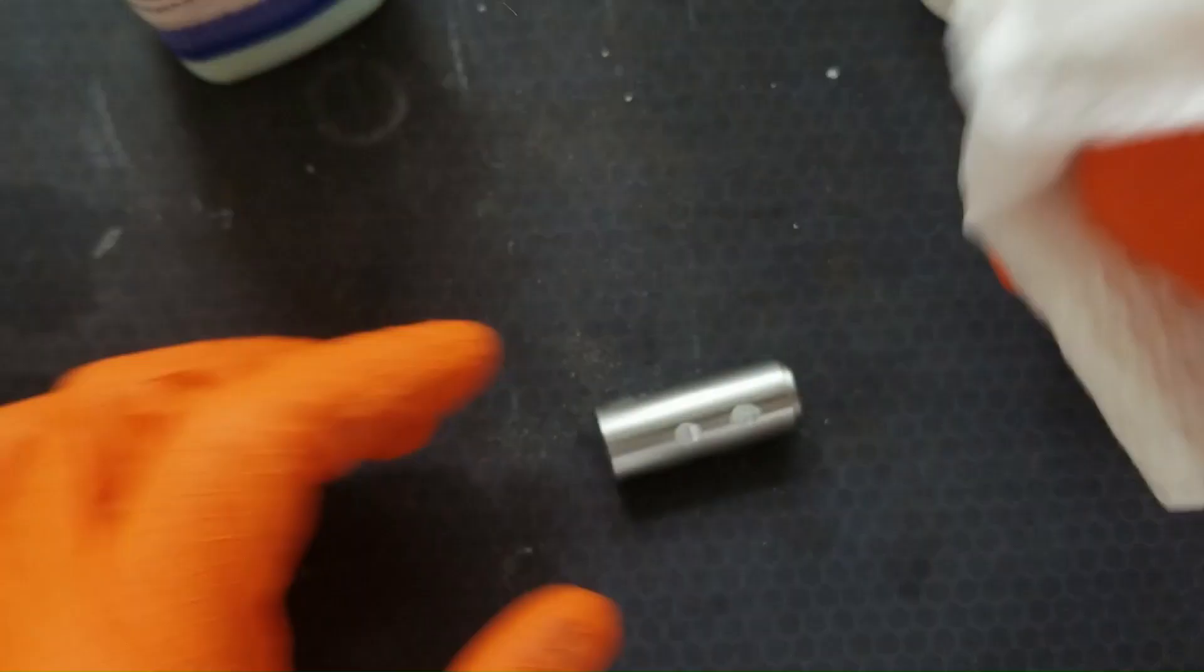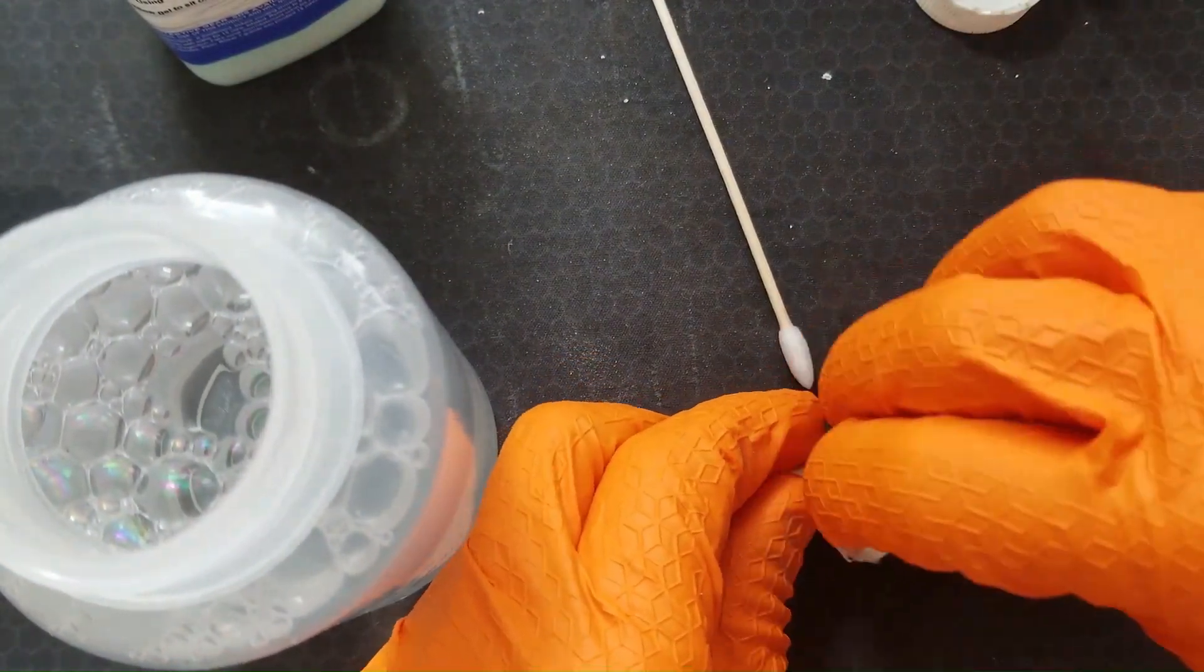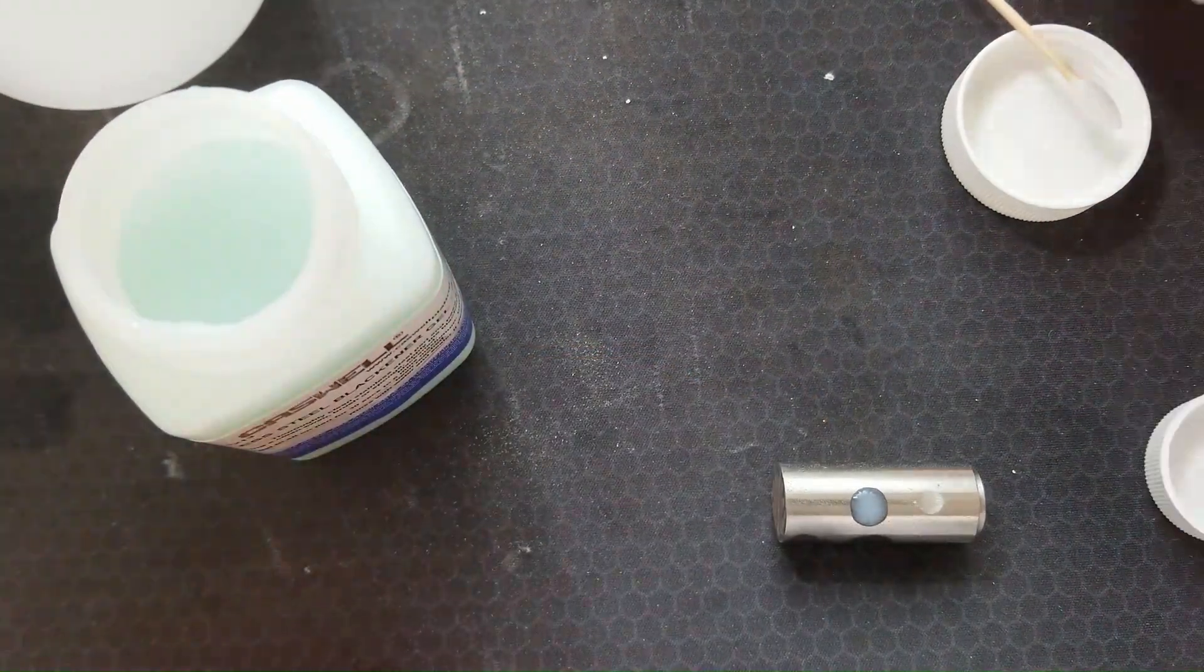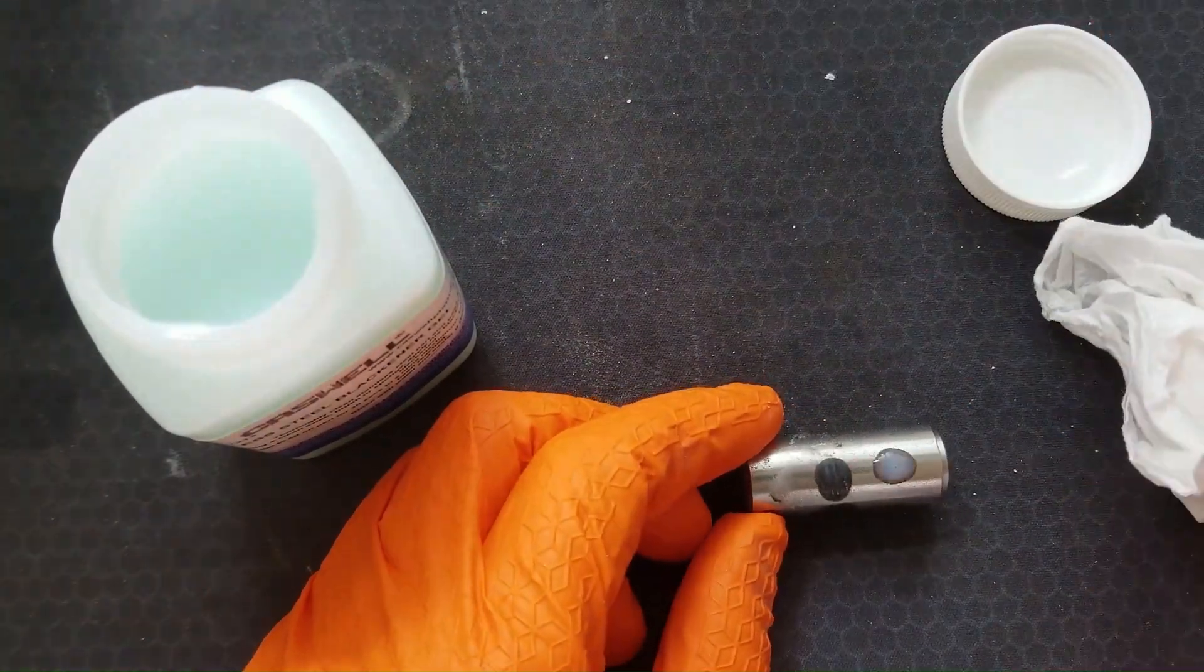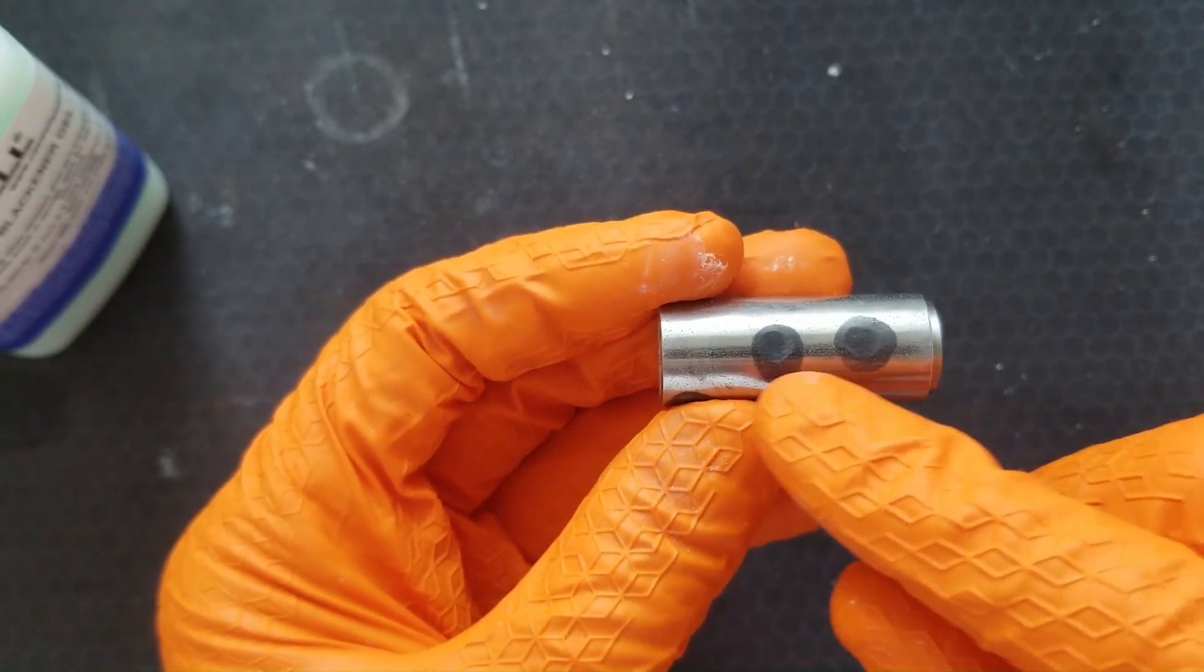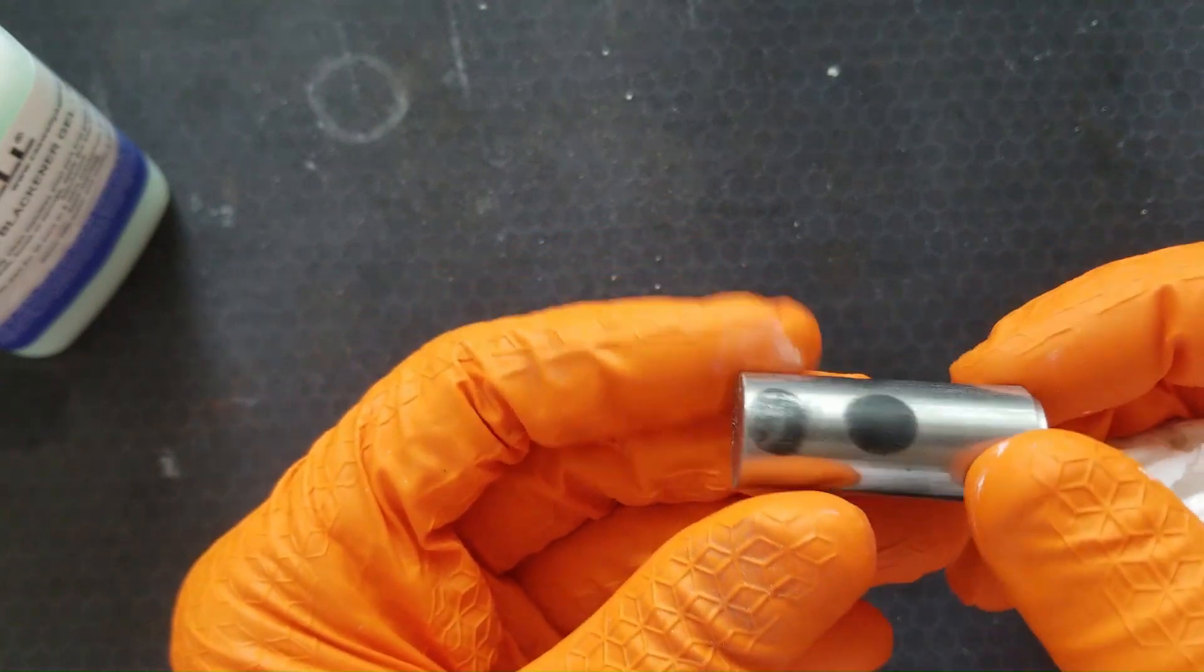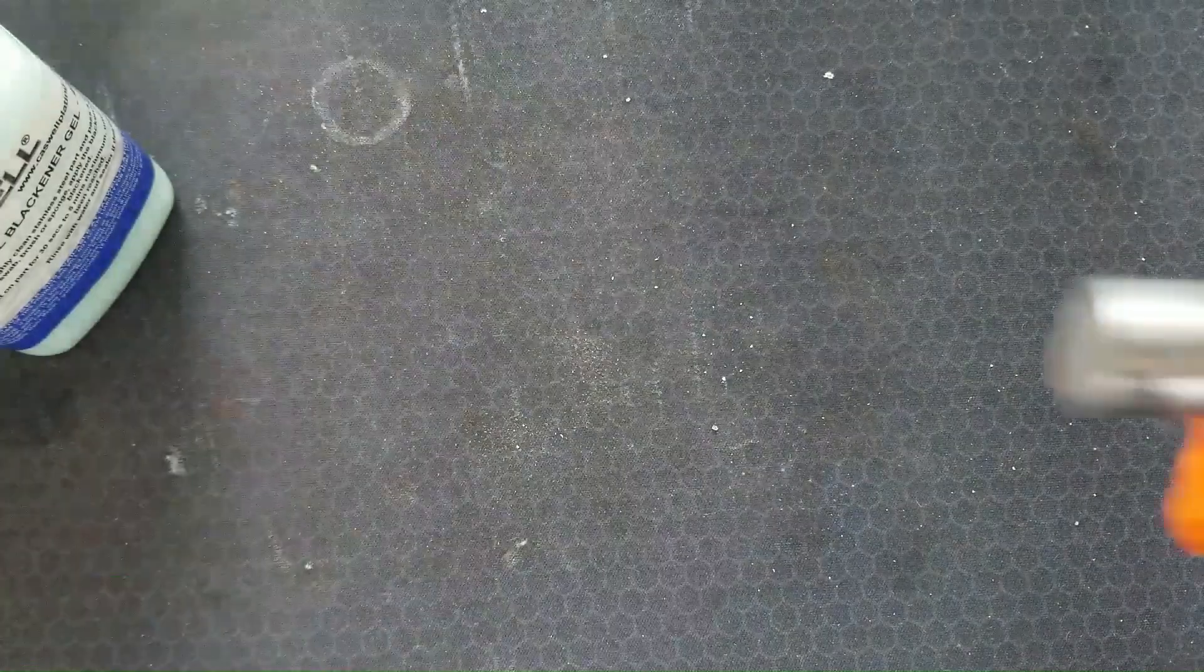Here I'm just using my Dremel and sanding drum to cut the two notches. Again going through the same cleaning process. After that I'm putting the blackening chemical right in one of the machined areas and then on the one next to it I am putting some hydrochloric acid and letting it sit there and etch the surface. Then putting the blackening chemical on the spot where I put the hydrochloric acid. So results on a freshly cut piece of the material, no muriatic acid and with muriatic acid, the results look to be about similar. So it seems that if the material is disturbed and it doesn't have a lot of time to create that passive oxide layer, maybe I can omit the hydrochloric acid prep.